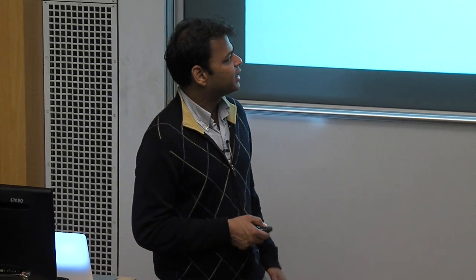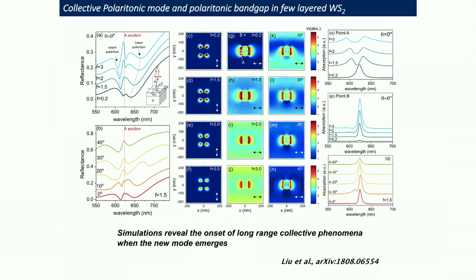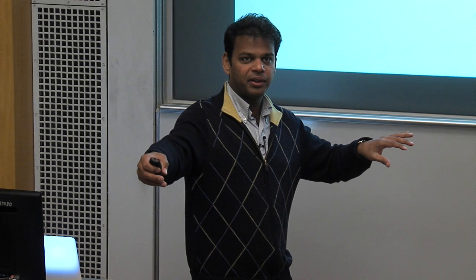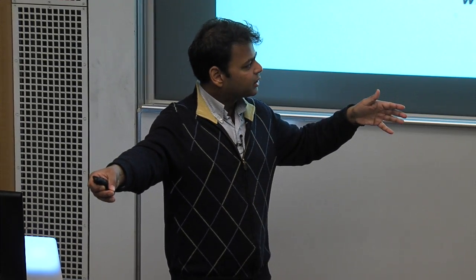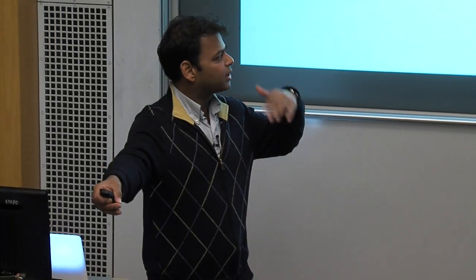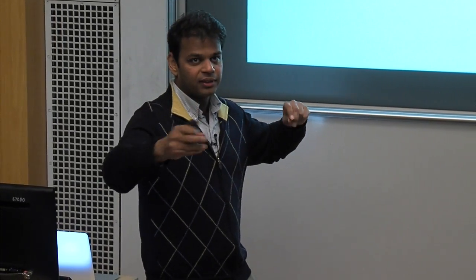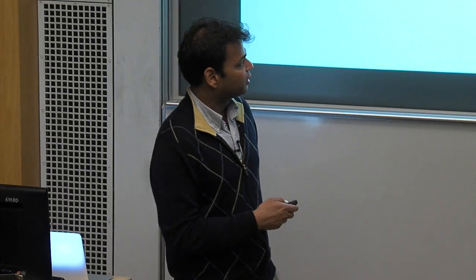So this was telling us that what we have is the emergence of very strong long-range collective phenomena in this system. What is happening is we have exciton-exciton interactions being mediated by the field. Those excitons would not have interacted if the density was low and if this was a bulk semiconductor. Because this is a two-dimensional semiconductor, the screening is weak, so the excitons can in principle interact, but they don't interact so strongly in the monolayer case. As we start increasing the density, they're forced to interact, but mediated by the field. So the field is important, okay?